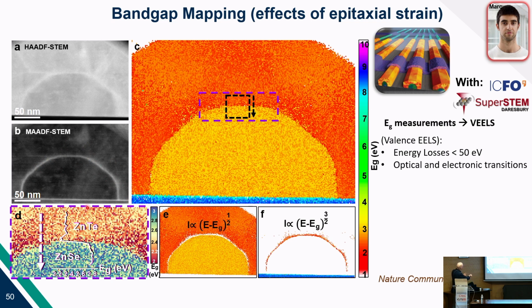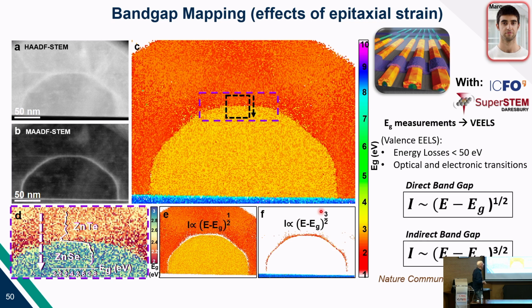You see that the material is more or less homogeneous, but at the interface, the strain is super high. And this is what you can see here. Exactly at the interface, you have a transition of the band gap from direct to indirect. So there is a small decrease in the band gap at the interface, but this is not the main point. The main point is that it goes from direct to indirect band gap, which is a really good result.